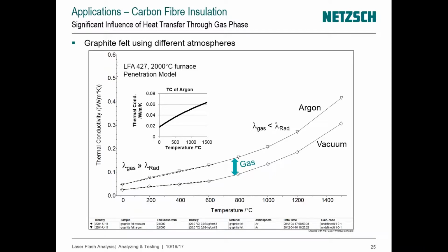As expected, you can see the thermal conductivity when the test is done with a purging atmosphere, in that case argon, compared to what would be obtained when vacuum is being applied. In that case, we are really using a pretty deep vacuum, and you see the difference. Essentially, the matrix, the core material itself, is far less conductive than it would appear whenever the contribution of the purging gas, in that case argon, is taken into account.